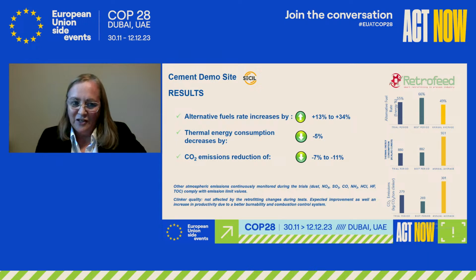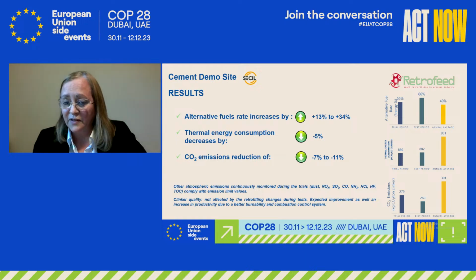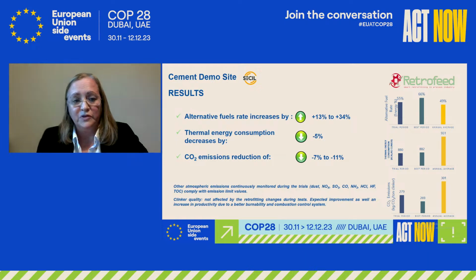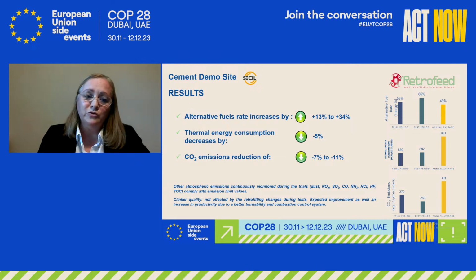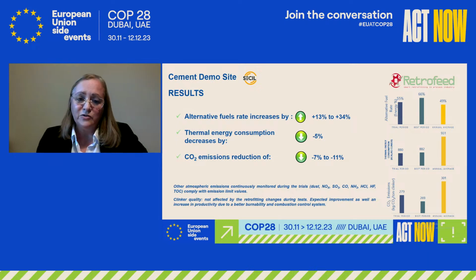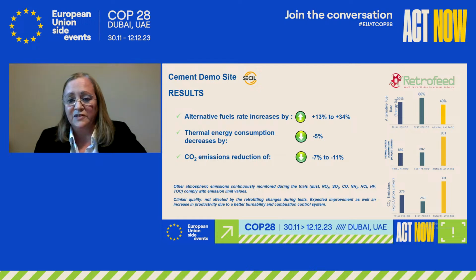The results we achieved with all these implementations are very interesting. We have an increase of the alternative fuels rate of about 13 to 34%, depending on the type of fuels that we are using. We had a reduction in thermal energy of about 5%. As you know, when we increase the rate, normally we lose production and we lose efficiency. That was not the case here. So this leads us to a CO2 emissions reduction of about 7 to 11%. So very, very interesting results. And the last slide, please.